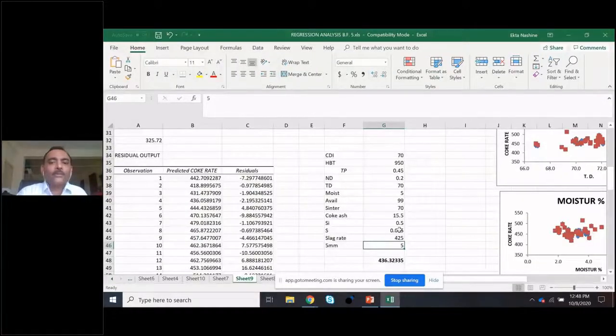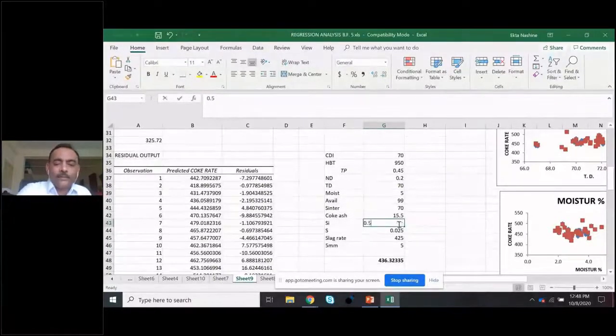Same for the case of silicon also. If instead of 0.5, I am able to run the furnace at lower silicon, let's say 0.35, my coke rate again reduces over 110.